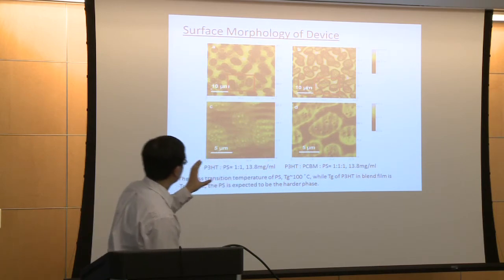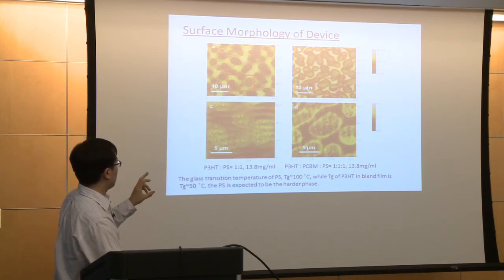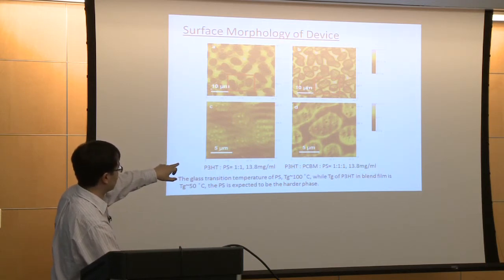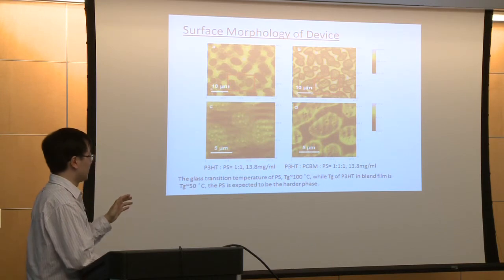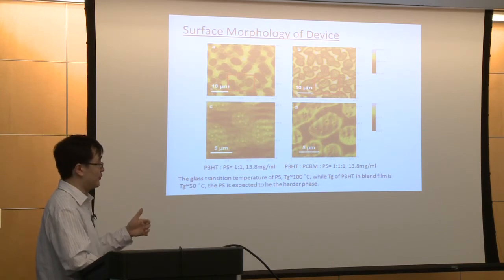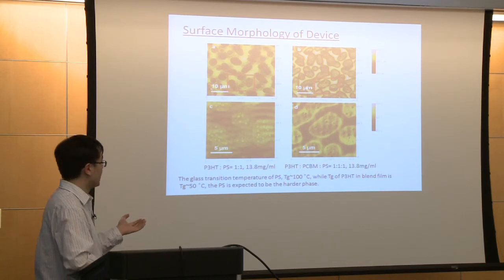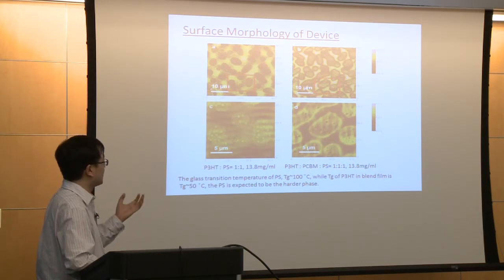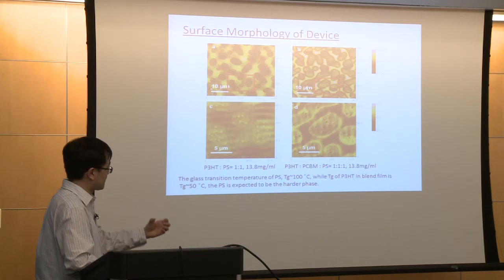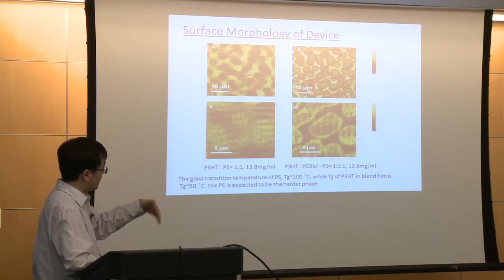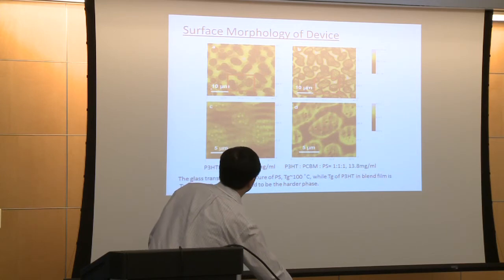Maybe you cannot see clearly from here, but the continuous area in figure D is darker than the certain domains on the surface, which means that area is harder than the other area. By comparing the glass transition temperature, which is 100 degrees C for polystyrene and 50 degrees C for P3HT, that dark area or the harder material must be polystyrene, and the softer area should be P3HT. So we confirm that the small domain should be P3HT, and the continuous area should be polystyrene.